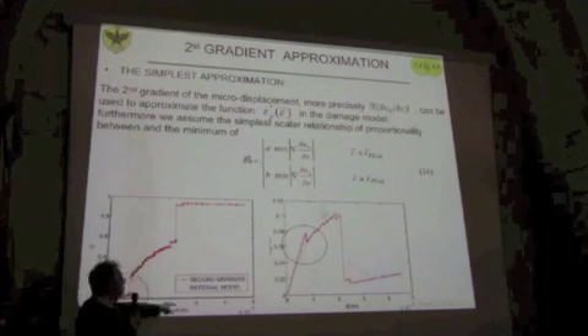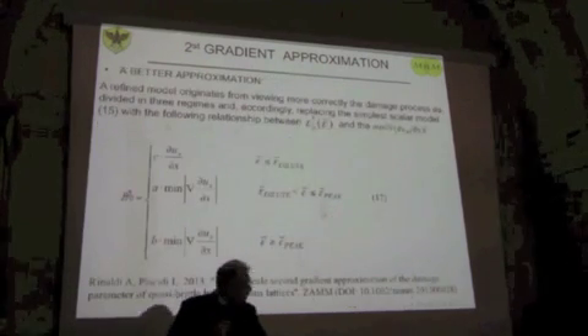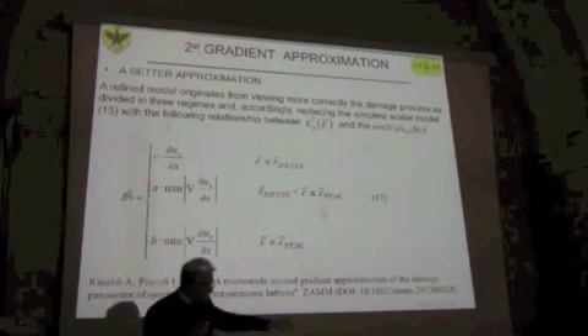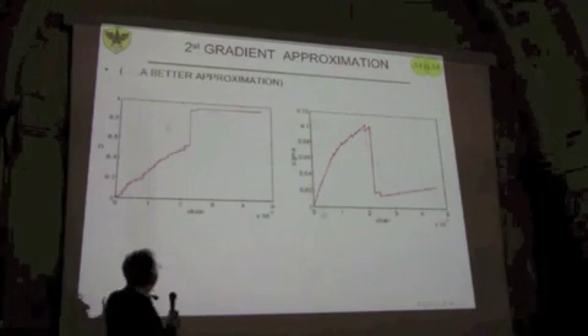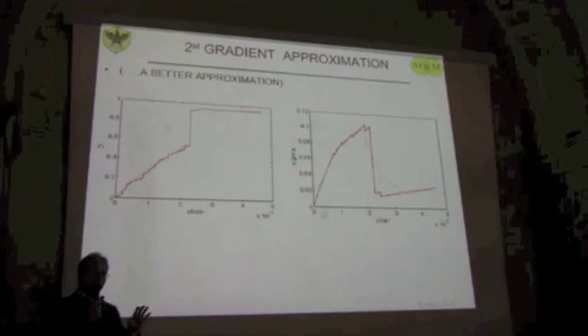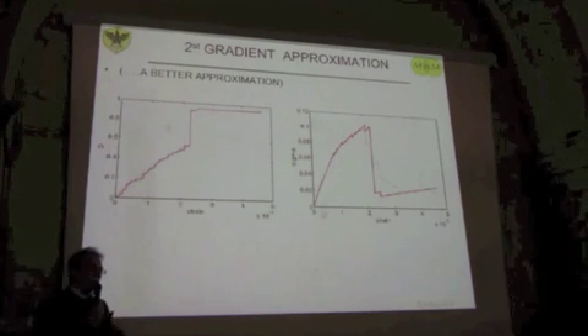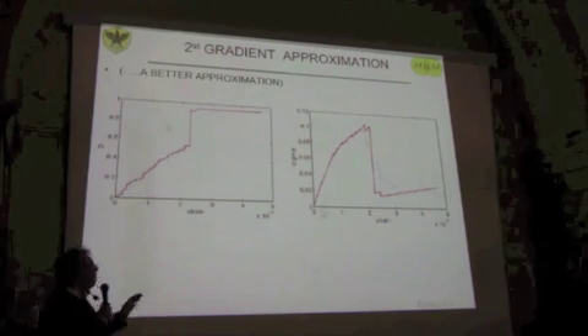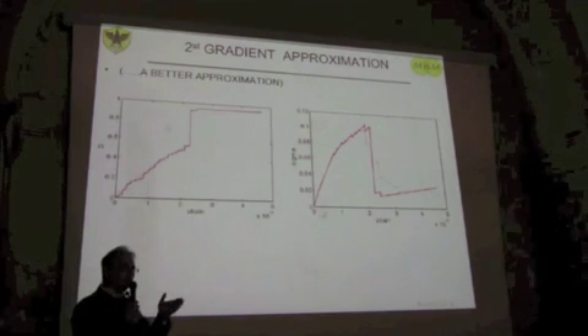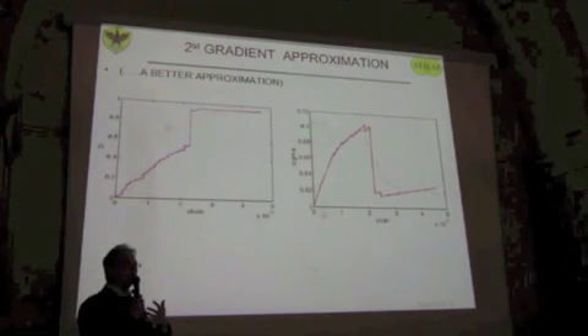However, there is still some problem because I have this problem here for small damage density. So what I do, I just make a different approximation for small strain. And essentially, I come up with this model, and I stop here just to show that by using a second gradient displacement, I'm throwing it inside my rational model, now I have a continuum quantity that I can measure experimentally, and I have enormously simplified my model, and I have an approximated model that actually matches the simulation results pretty nicely. So there is definitely now a continuum counterpart that is physically based to the rational model.